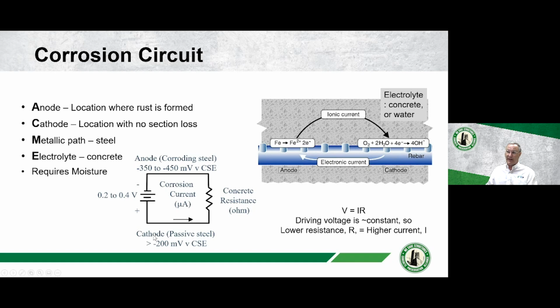And then you have the cathode, or the passive steel, which is the normal condition, like when you put rebar into concrete. There's no chlorides. It gets happy. It's sitting there in this alkaline environment. It initially corrodes and creates a passive oxide film on the surface, and the potential of that bar becomes around 200 millivolts or above.